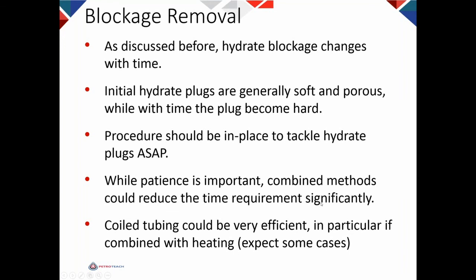But you need to be patient. That's a key point. Once you understand that it is beyond your control, how long will hydrate dissociation take? Because you can only exert a certain delta P. And there was one case, the pipeline had very good insulation. Seabed temperature was around 4 degrees, and the minimum we could go was 0. So the driving force was 4 degrees, and the time required for hydrate dissociation was almost 1 year. So you need to be aware of the limitation, especially when the ambient temperature is low and insulation is good.